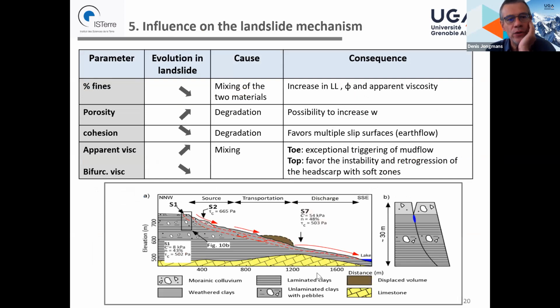And so if we look at the influence of this geotechnical test on the landslide mechanism, what we obtained is that the percentage of fines decreases inside the landslides, and our interpretation is that it is probably due to the mixing of the 2 materials that I showed you, and the consequence is the increase in liquid limit, in the friction angle and in the apparent viscosity. The porosity increases inside the landslide, caused by the degradation of the clay that was observed in other landslides all over the world, and it gives, of course, the possibility to increase the water content.